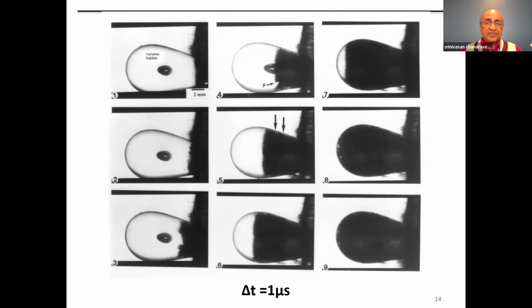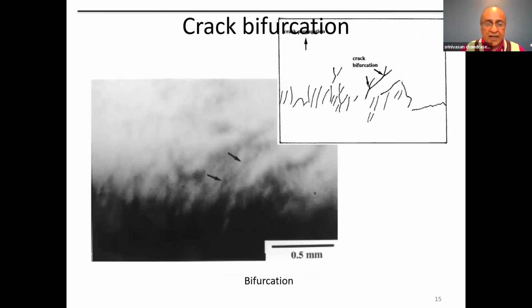You see there's a little blob in the middle, which is the vacuole. And the vacuole didn't seem to play any big role in changing the velocity of the fracture front or anything like that. We couldn't measure. So a characteristic feature of this fracture front is always the appearance of these finger-like protrusions. If you blow up one of these frames so that the magnification is increased, these fronts are seen, and we have recreated these fingers in the form of a line diagram in the top right.